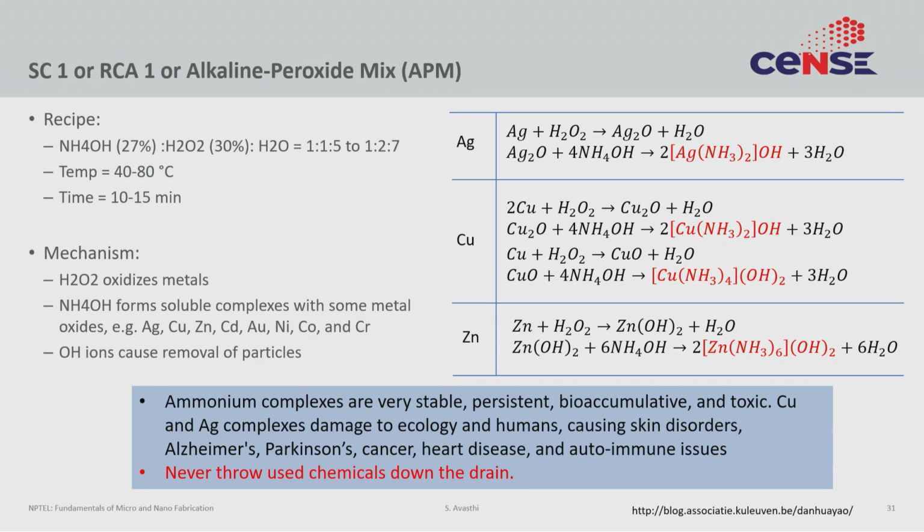The temperature of the solution is around 40 to 80 degrees C. It does not self-heat as much because there is a lot more water in this. So you have to externally heat it either using a hot plate or through a bath. And typically you do this clean for 10 to 15 minutes, which is the same as Piranha before.